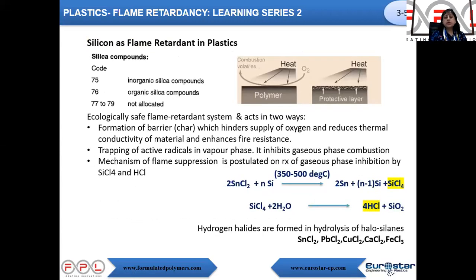Then another system which we are considering is silicon, which is a very eco-friendly system. You have the inorganic silica compounds and the organic compounds, which are normally the silicones. These are ecologically safe flame retardant systems, and they act basically in two ways. One is the formation of a protective layer, a barrier which reduces the thermal conductivity of the material, and as a result, it enhances the fire resistance. The other part is the trapping of active radicals in the vapor phase, so it inhibits gaseous phase combustion also. If we look at the mechanism, it's postulated here.